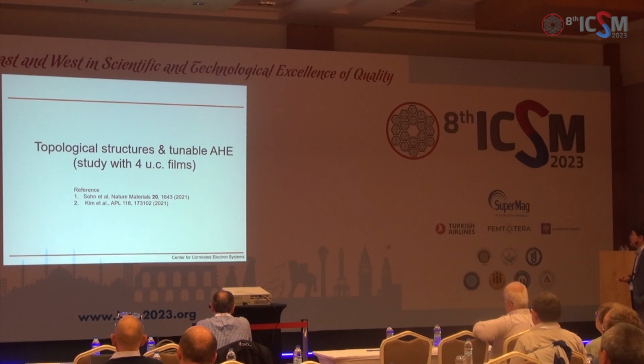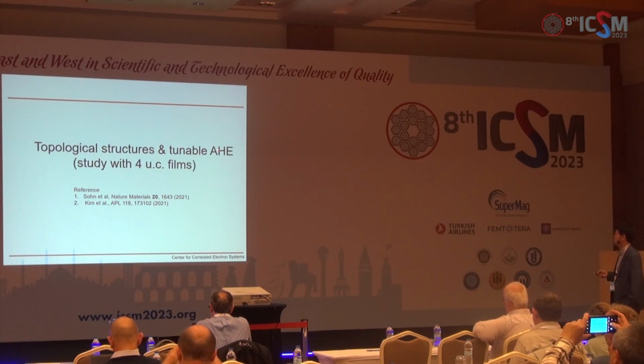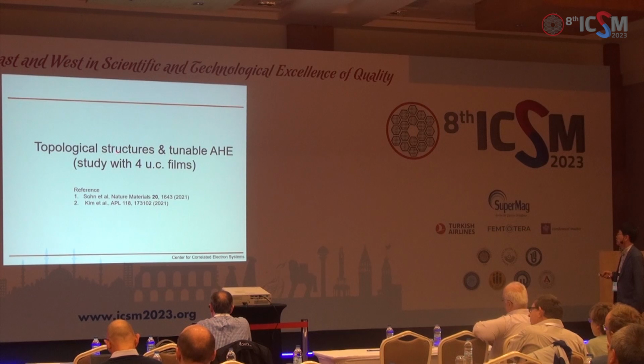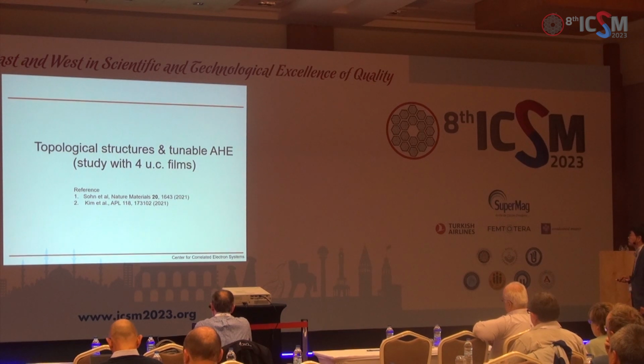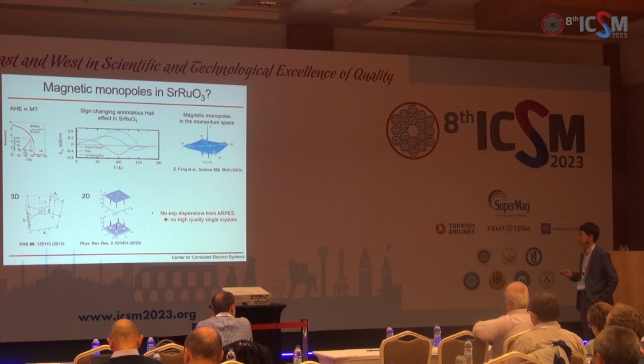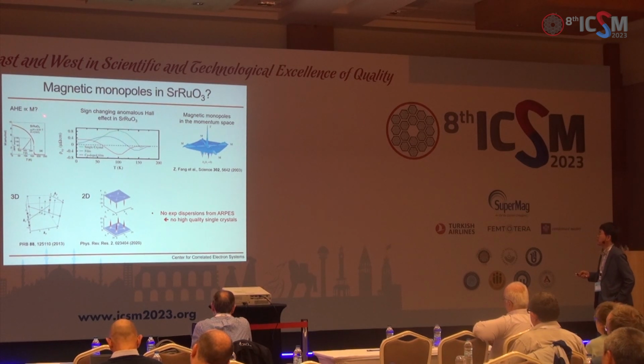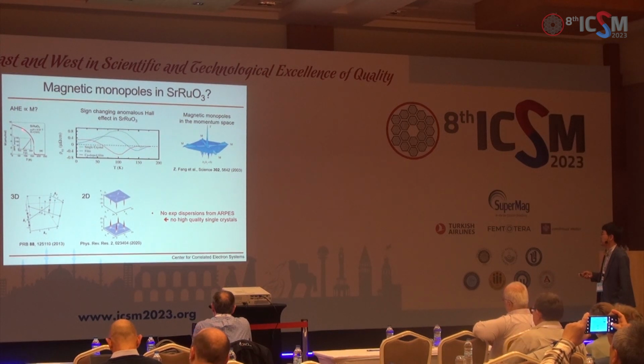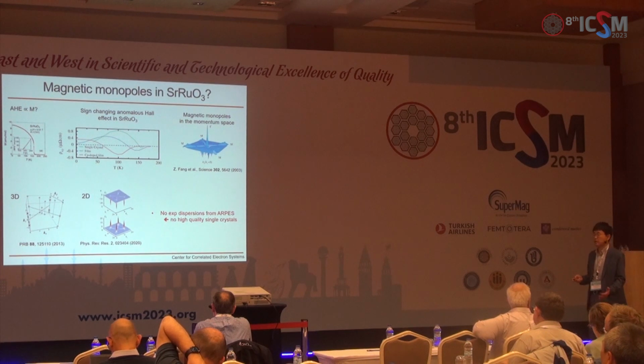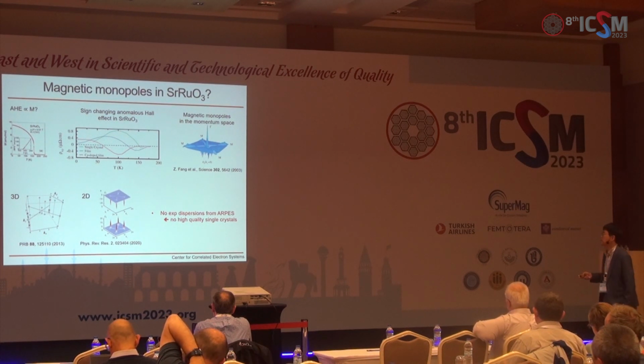Now, getting to interesting physics here. Let me first talk about these topological structures and tunable anomalous Hall effect in strontium ruthenate thin films. This was published in these 2 papers. So, the anomalous Hall effect was found more than 100 years ago, as you know, and it's supposed to be roughly proportional to magnetization. And if you recall the magnetization as a function of temperature, it looks like this. And this doesn't change whether you look at films or bulk.